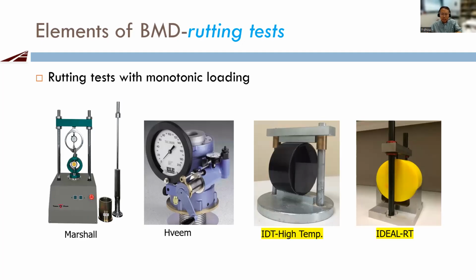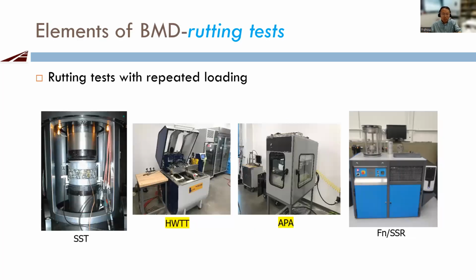And this one is a high temperature IDT test. This is the most recent one, where we developed the IDEAL rutting test, IDEAL-RT. This is the major difference when you look at this test and this test. This one has one supporting bar at the bottom, mainly measuring the tension, and this one has two supports at the bottom here, and the top is loading here. You are generating shearing stress, because rutting is really caused by shearing.